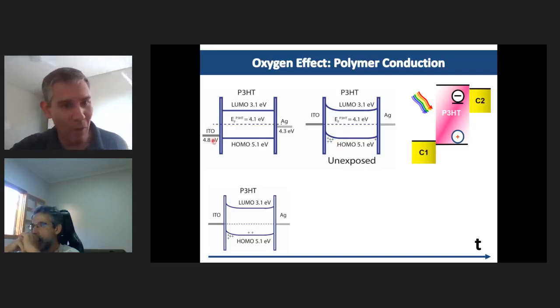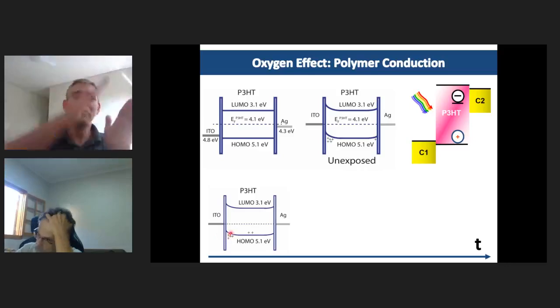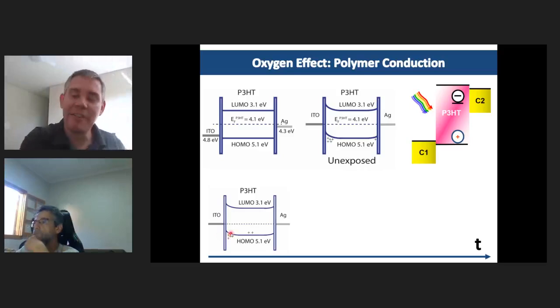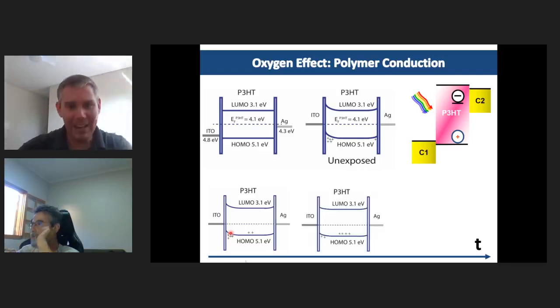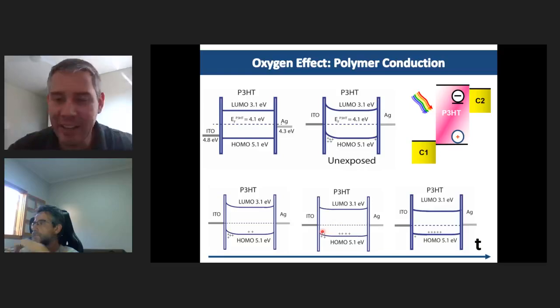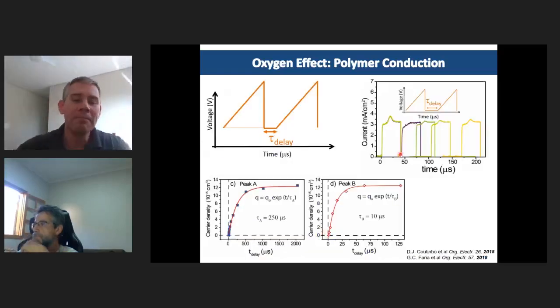And by moving towards the HOMO of the material, I diminish the energy gap between the Fermi level of the neutral P3HT and the work function of ITO. And therefore, I diminish the amount of charges that need to be added to the interface to bend and get the interface into equilibrium. And that's the reason peak A diminishes, because the Fermi level is moving down towards the HOMO. So as time goes by, you add more and more p-doping to the P3HT, the more the Fermi level moves toward the HOMO, the smaller is the reservoir of charge at the interface, up to the time that basically that reservoir disappears, which is basically what we saw in the results.